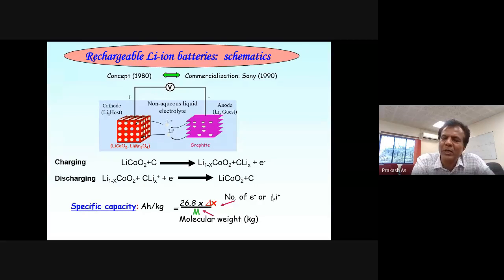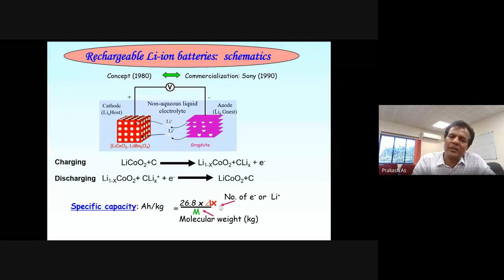96,500 is the coulombs in 1 mole of electrons, and you divide that by 3,600 seconds in 1 hour. It is 26.8 ampere hour into delta X. Delta X is the number of moles of lithium or electrons involved in this reaction. For example, if you remove 50% of lithium from lithium cobalt oxide, then this is 0.5, right? And M is the molecular weight of lithium cobalt oxide. It's typically about 96, 97 or so.